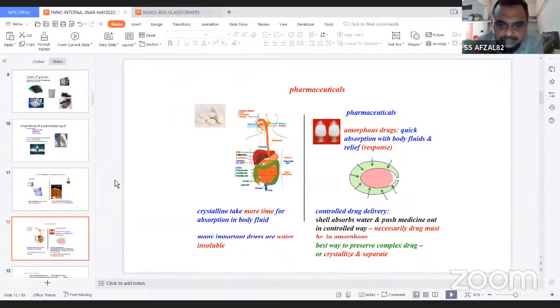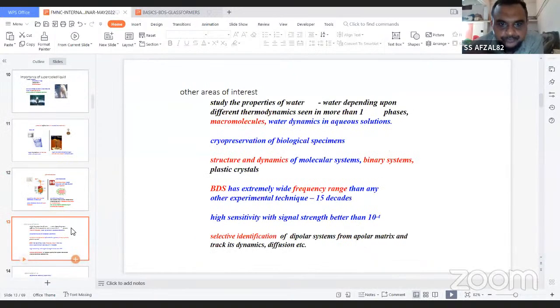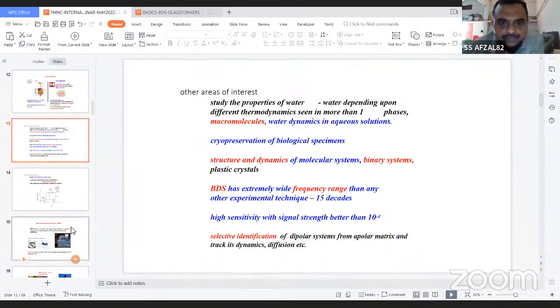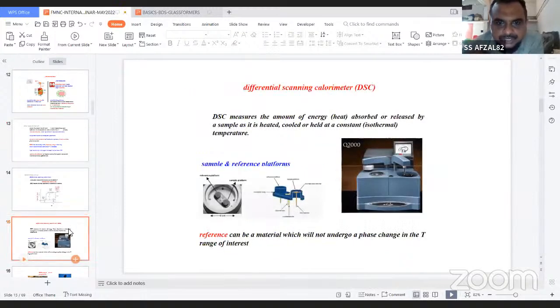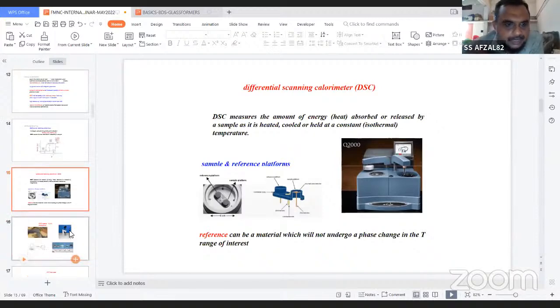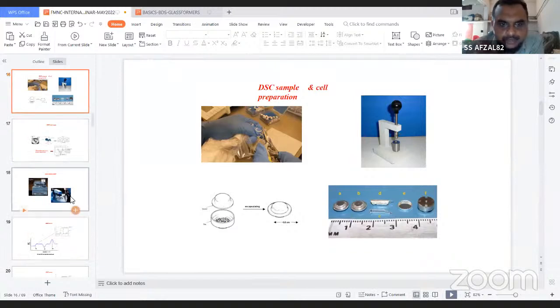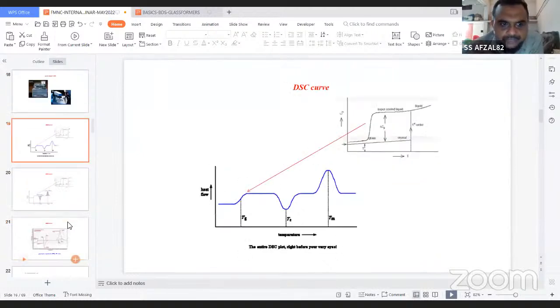But the problem is the amorphous phase, during the shelf life, may return back to the crystalline phase. So we want to study the stability of the amorphous phase in the shelf life. For that, we have to characterize the supercooled liquid state and the glassy state using this molecular dynamics. So we can estimate the stability of the amorphous phase. The different areas of interest of this glassy state are listed in this slide. And for understanding the glass transition temperature, we use differential scanning calorimetry. As we can see, using the endothermic exothermic curve, we can find the glass transition temperature of the sample.